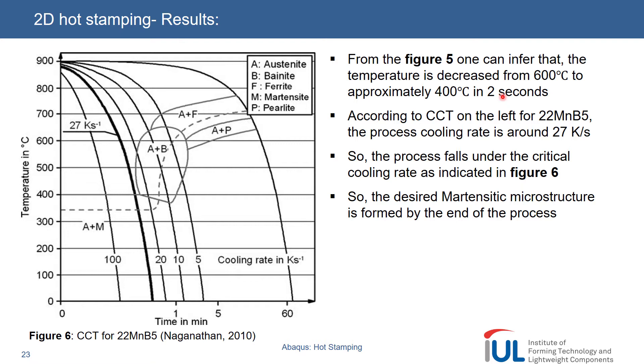You could justify to your bosses that you will end up with a martensitic microstructure. This is part of what we wanted to get out of the simulation. As a rule of thumb, this is the way it will turn out even without including all the microstructural effects in the simulation, because they will not significantly affect the general outcome of the cooling rate. This is mostly dominated by the thermal properties of the materials and the general setup - it's interesting that we can get this information out of our simulation.